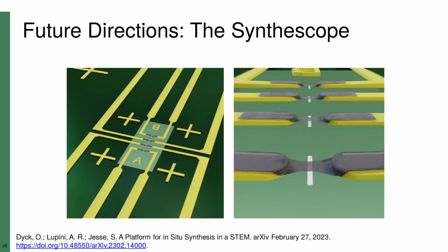Because we are interested in ultimately making use of these fabrication capabilities, we have also put a significant amount of effort in developing STEM-compatible devices that are fabricated on the wafer scale. These devices have an electron-transparent window at the center, which allows high-resolution imaging during operation and will allow us to use the e-beam to modify the device at the atomic scale.